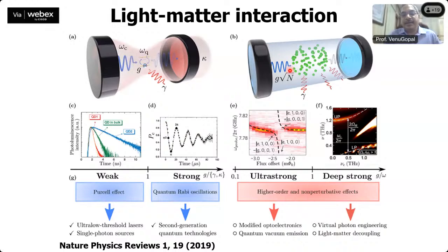However, people are now looking at domains with much stronger interaction strength, much different from that of the weak and strong coupling regimes. So these are the non-perturbative regimes, where instead of having one single atom, you have, for example, an ensemble of atoms, where there are n number of atoms inside a cavity. To go from weak to strong coupling regime, we have to have very high Q factor cavities. But the Q factors of the cavities have certain limitations. So the other way to go is by increasing the number of atoms or number of two-level systems inside the cavity. Once you have this ensemble of two-level systems, we now have cooperativity effects where we no longer talk about a single atom, but these act like a collective ensemble of atoms. Right? And here the coupling constant is no longer G, but it is G times square root n.